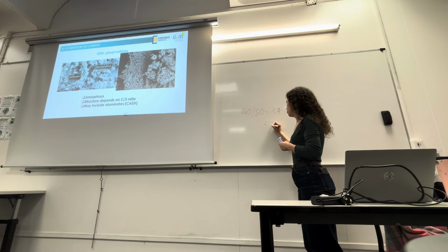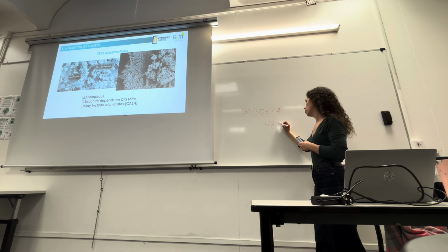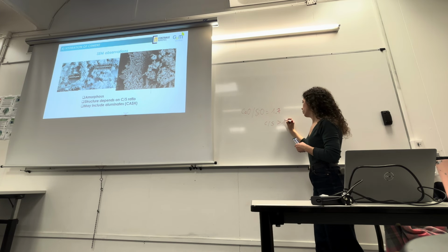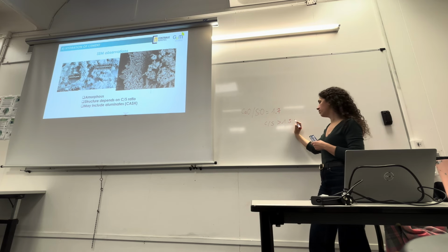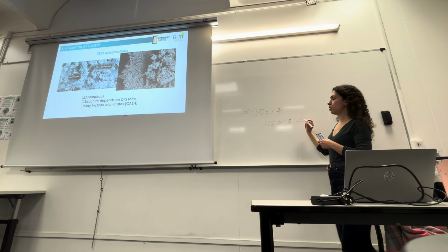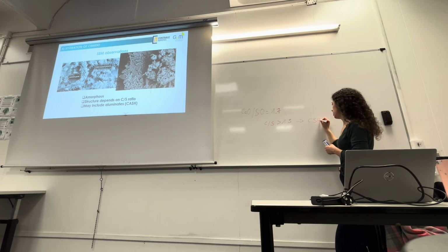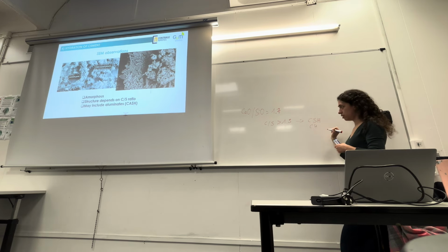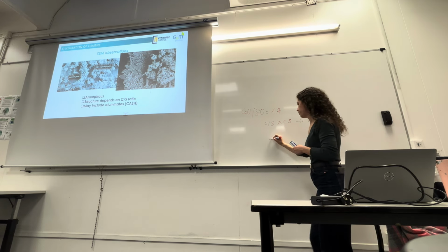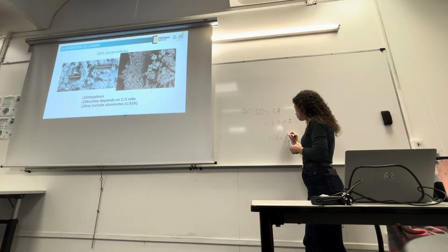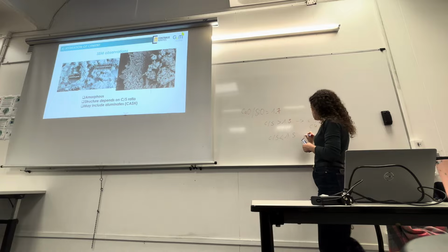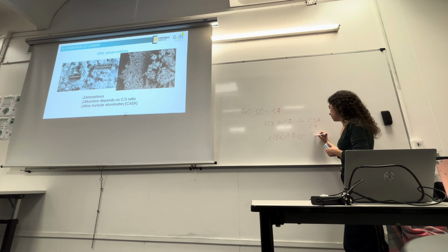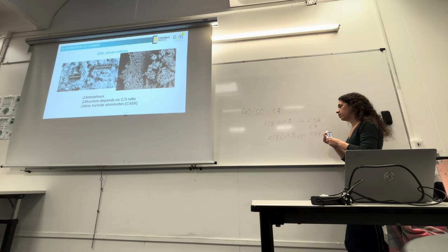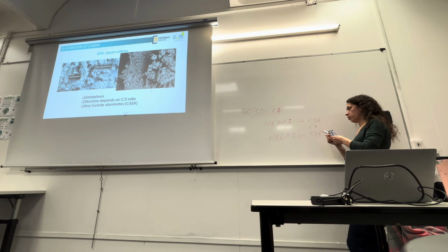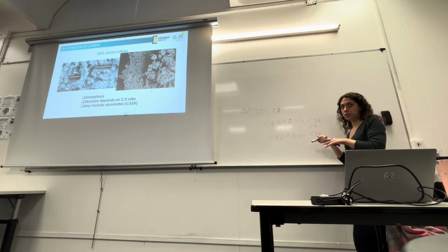If you have a C/S ratio over 1.5, it means your CSH are not pure. You will have CSH and carbonate. If you are lower than 1.5, you will only have pure CSH. I mean pure in the sense that you won't form other compounds. You will only form CSH.